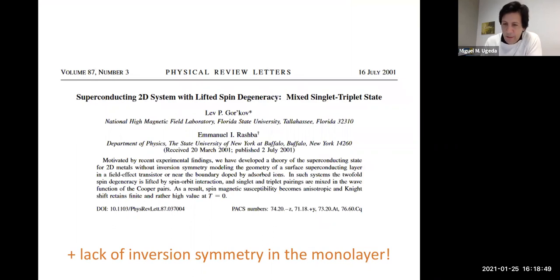It's been theorized that any two-dimensional superconductor in the presence of a strong spin orbit coupling, which is the case in the absence of inversion symmetry, develops a strong spin orbit coupling, because the inversion symmetry is broken, and therefore it's not canceled, right? In that case, the bands become spin split, lifting the degeneracy, and that should lead to a mixed singlet and triplet state, not just a singlet. So the system should, in other words, become unconventional naturally in two dimensions.